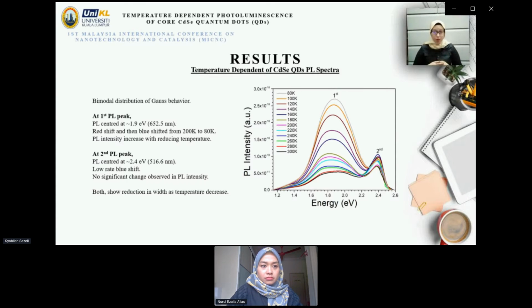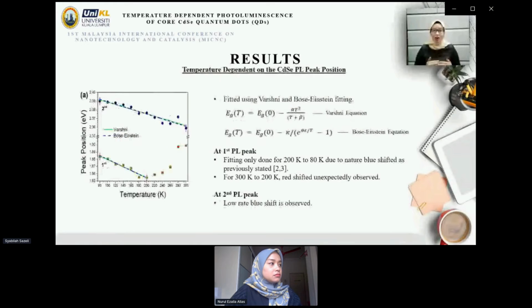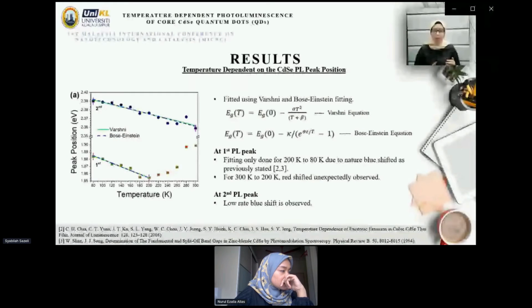For the PL spectra, we can observe it is almost identical for both spectra. However, upon close inspection, there is a reduction in width as temperature decreases. Next is the result of temperature dependence on cadmium selenide quantum dots PL peak position. This is the figure of PL peak position versus the temperature. The data are fitted using two fittings. First, the Varshni fitting. Second, the Bose-Einstein fitting.